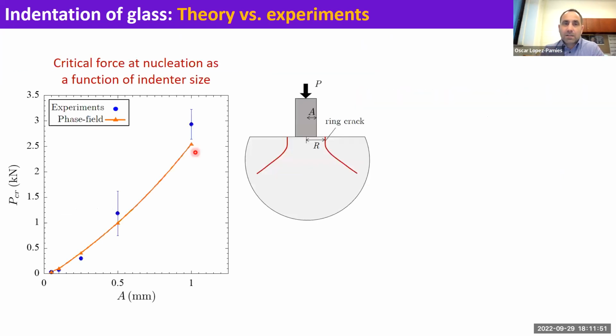All right, so we can compare with experiments. This is the critical force at which nucleation takes place for different radii of the indenter. And you can see here that we have quantitative agreement with the observations. Interestingly enough, as you make the indenter smaller, the force required to nucleate a crack is smaller.